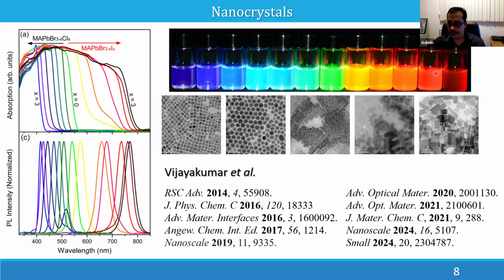to deep red color. Okay, so this is one way, and similarly you can get different structures like a cubic structure, octahedral structures, nanorods, and flake-like structures, or like bundled flakes like this, small flakes or bigger flakes like this. So you can have all kinds of flexibility. You can change the structure, you can change the morphology of the material. In all cases, you can tune the optical and electronic properties, and that is required for the device application. For optoelectronic application, you should have the flexibility to tune the optical and electronic properties the way you want.